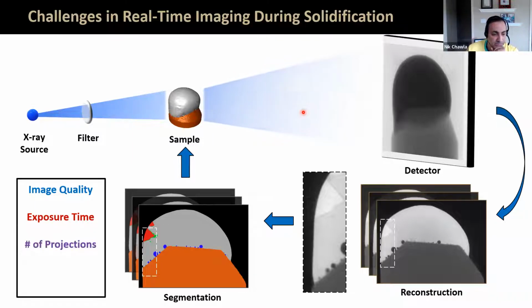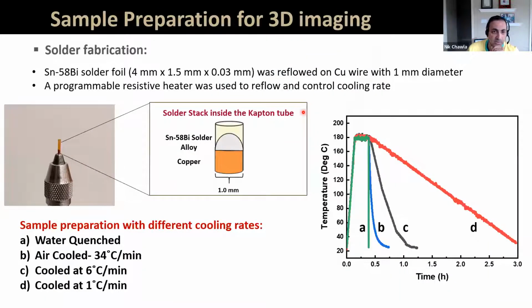exposure time. So if we can minimize the number of projections that we're taking during the scan, that would be better. And then we also need to get to the right range of energy for our particular sample. In this case, we have tin and we have bismuth. So these are some of the details of the actual experiment.